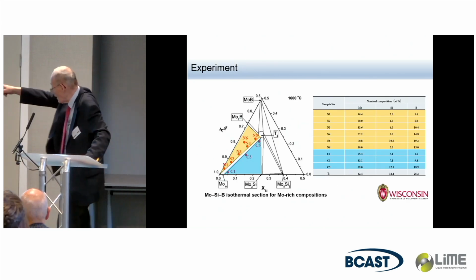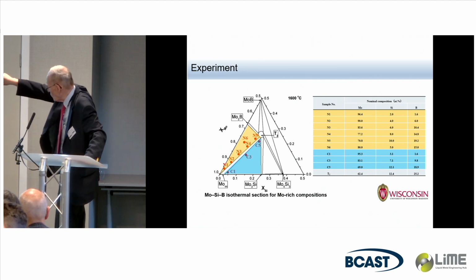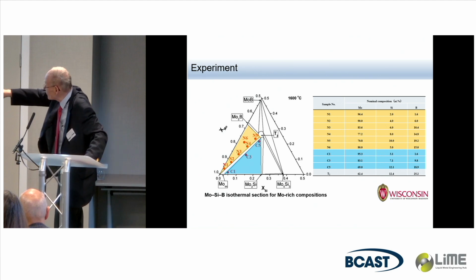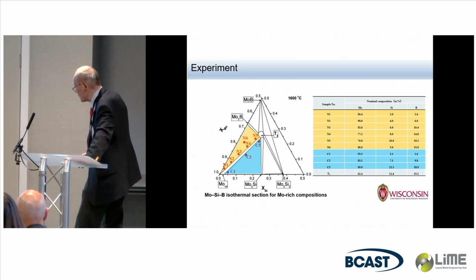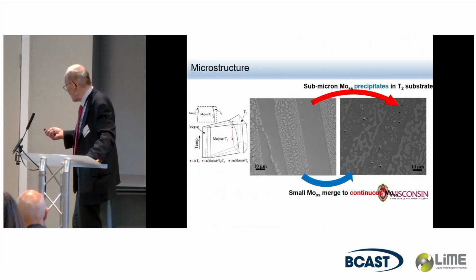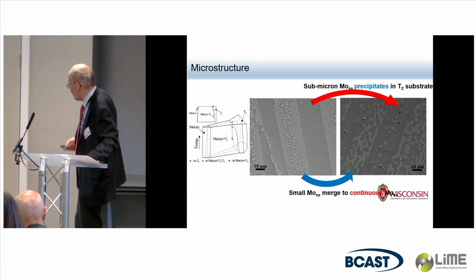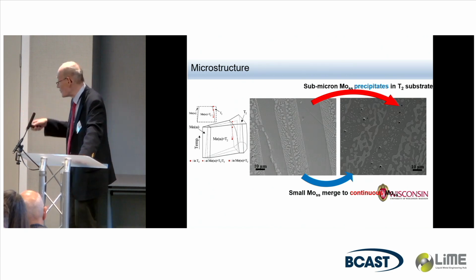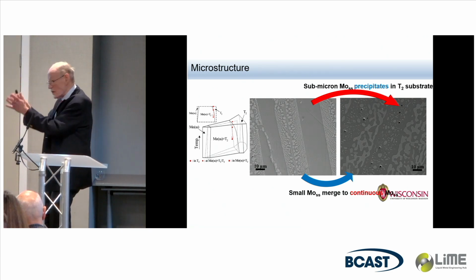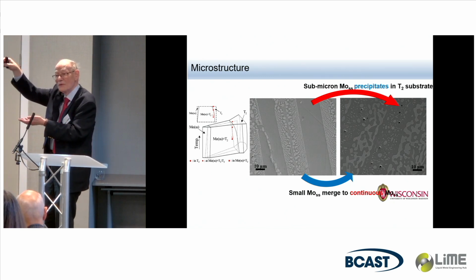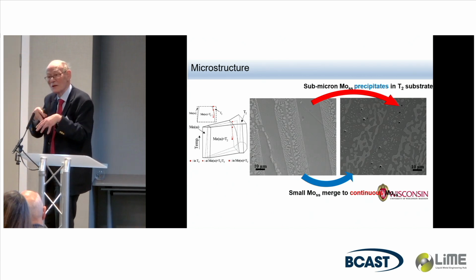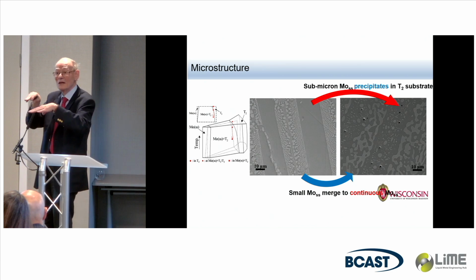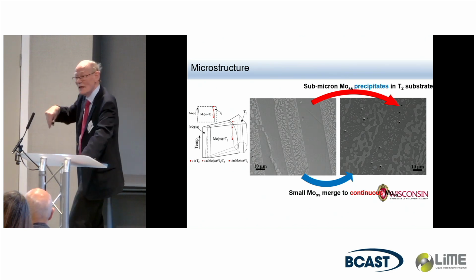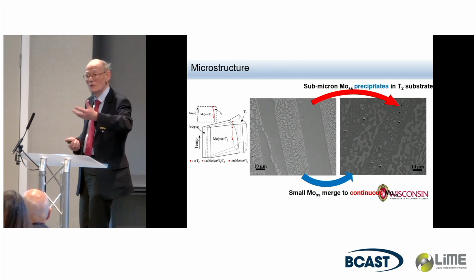And we compared alloys N3, which is molybdenum T2 on the Mo2B side, and C3, which is the molybdenum Mo3Si T2 side. So they're just on both sides of the two-phase field between molybdenum and the T2 phase. And when we did that, we found not only did we reduce the solubility, but we got precipitates of molybdenum in the T2 phase. That's because as you go up in temperature, entropy opens up the T2 phase, and so as you cool down from the melt, the T2 phase is supersaturated with molybdenum. And so as you anneal at 1600, you actually precipitate molybdenum inside the intermetallic, which is sort of the reverse of what we normally think of.